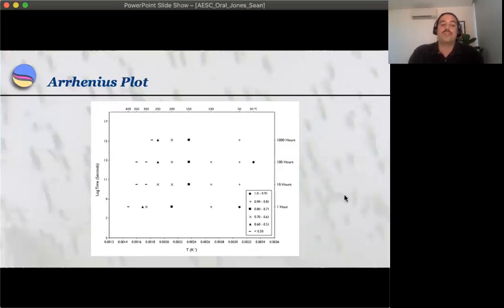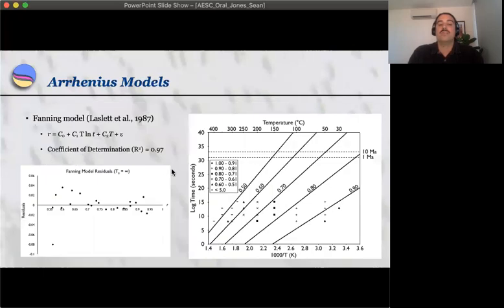To extrapolate the laboratory annealing results to geological timescales, an empirical model is presented today, which has been used to determine a functional form of fission track annealing kinetics. Here is the fanning model from Laslett, which shows the full data set with contours of equal length reduction extrapolated to geological timescales. You can see that the model has slopes of contour lines that change with the degree of annealing.